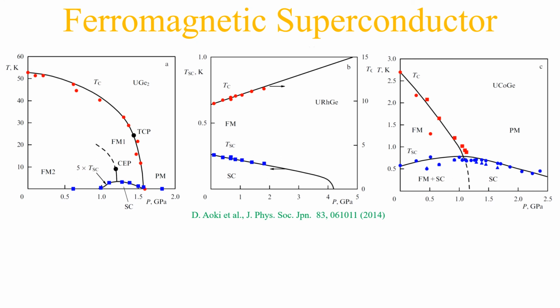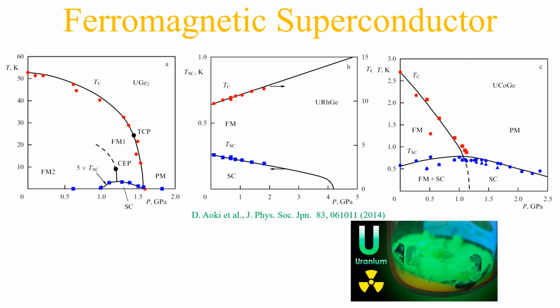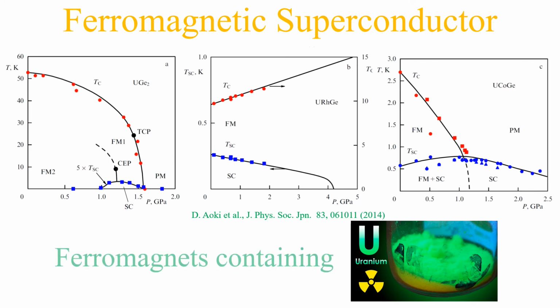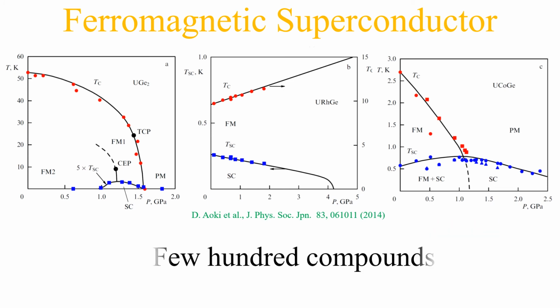If we look closely, they share one more feature. They all contain uranium, which we believe gives rise to ferromagnetism. So we decided to look for superconductors in ferromagnetic compounds containing uranium. Now, this is a very good starting point, because by doing this, we just shrink the search space from 60,000 inorganic compounds to a few hundred compounds.